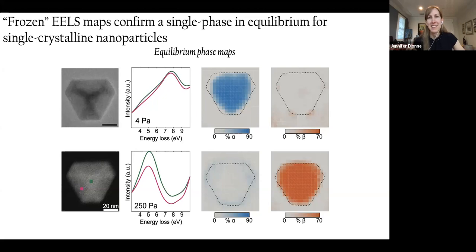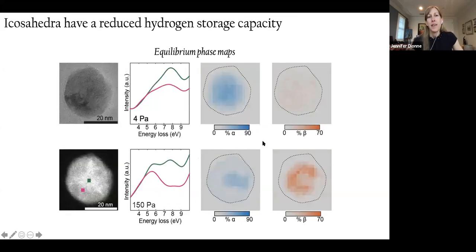So at low hydrogen pressures, we're always in the alpha phase. At higher hydrogen pressures, we're always in the beta phase. That is in contrast to the icosahedra, these polycrystalline nanoparticles, where there are certain hydrogen pressures where you find a multitude of phases in equilibrium.